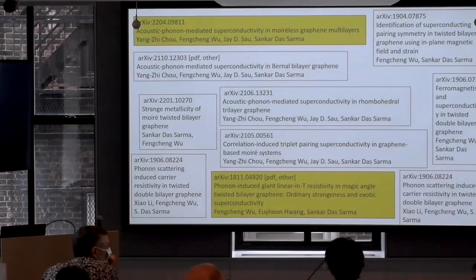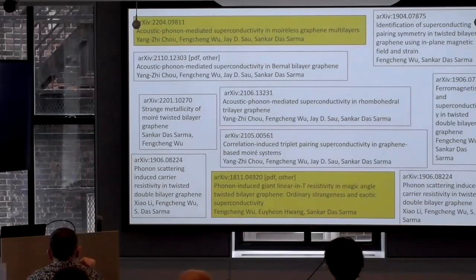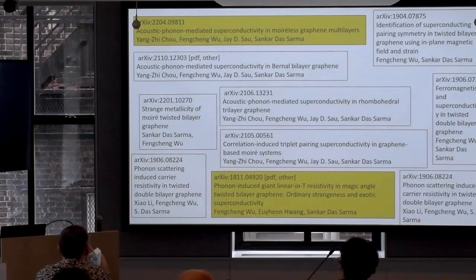Machines don't work. So I was just wondering, in the resistivity calculations, are those including all of the phonons? No, just the resistivity calculation that's going on now is including all the phonons. But everything I showed you is just acoustic phonon. Okay. And then I also wanted to ask, so you kind of flashed it, the different stackings of graphene seem to have different power law dependencies on temperature. Like there was a T to the sixth and a T to the fourth.